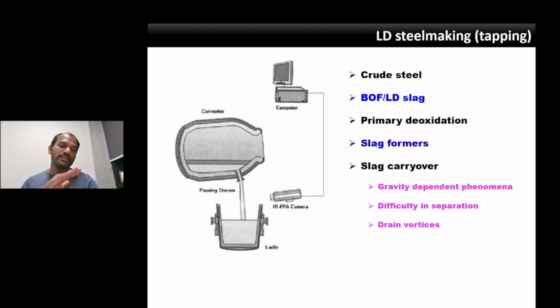So as soon as the tapping is going to be over, at the end of the tapping process, because of a gravity dependent thing, the vortex formation will take place. And once this vortex formation is incepted, the upper phase, that is the slag, will be carried over into the stream that is going into the ladle. So this process is basically called slag carryover.